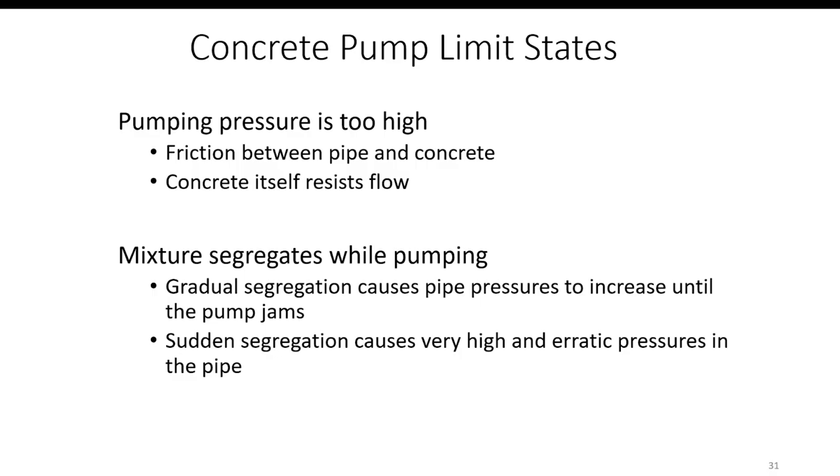If you get this segregation that starts to happen, it is dangerous, extremely dangerous. Gradual segregation causes the pipe pressures to slowly go up until the pipe jams. If you get a sudden segregation, then it causes very high and erratic pressures inside the pipe. I'll show you what I'm talking about.